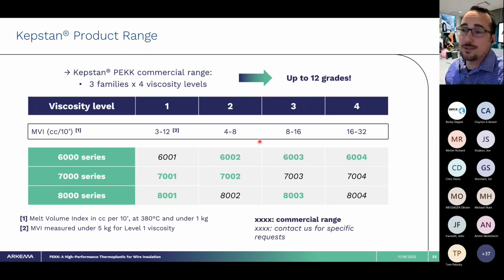And the last piece is we offer this in 12 grades relative to viscosity—the 6,000, 7,000, and 8,000 series, which control the melt temperature and crystallization kinetics. We've also got a variety of viscosity levels depending on process conditions. The 6004 series will have a much higher flow rate at temperature, which is great for compatible resins.